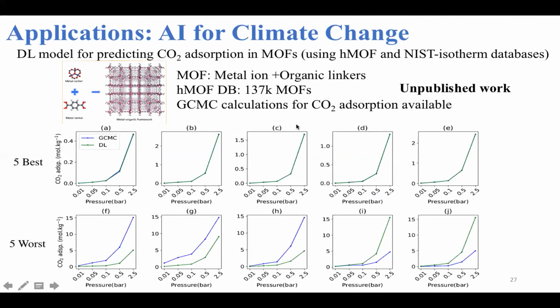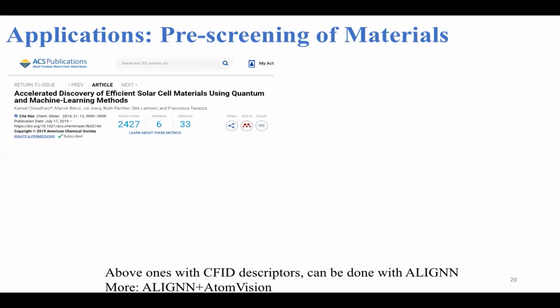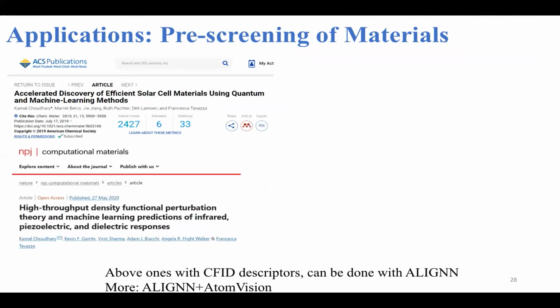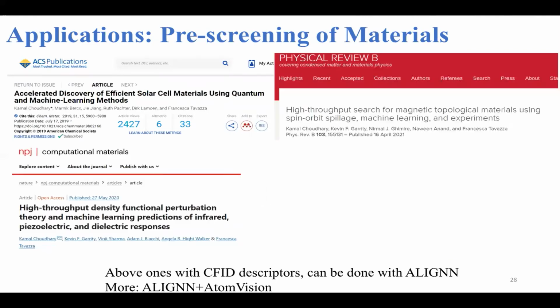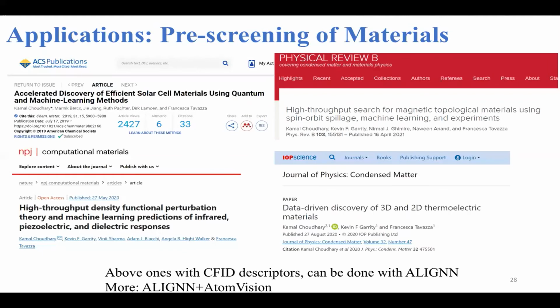So after we trained this model on hMOF, we actually tried this model on other MOF datasets such as CoRE MOF, and we then screened the best few MOFs that can be synthesized, that our experimental collaborator can grow in the lab and test this deep learning guided screening and so on. So in addition to this, we can screen materials such as solar cells, piezoelectric, dielectric materials, topological materials, thermoelectric materials, and so on. We have done this work with the CFID model, but we can definitely do this with the ALIGNN model.